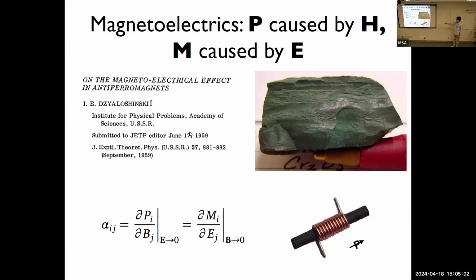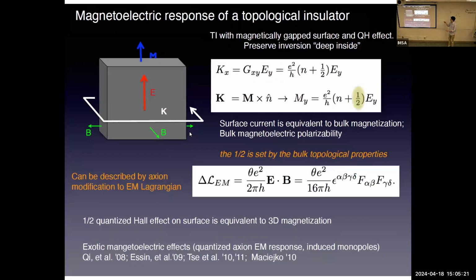And usually this value is random for different materials. For instance, in this case, it's chromium oxide. It could be like 0 or a very small number. But in case of TIs, they should be thought of as magnetoelectrics which also give a quantized response. This alpha is not just a random number, but something which is quantized, and you'll be seeing that in the next slide.